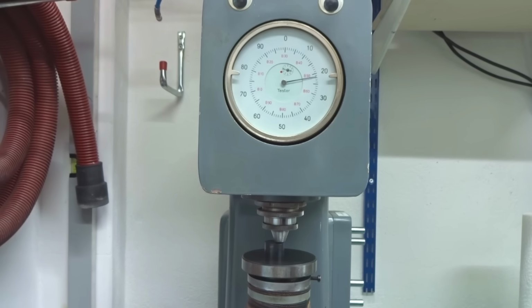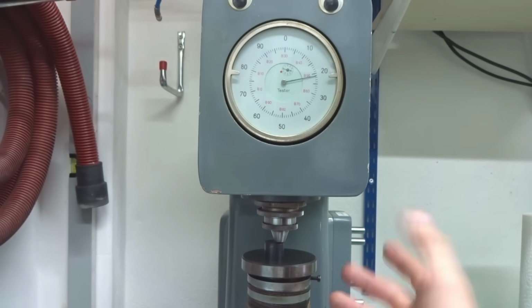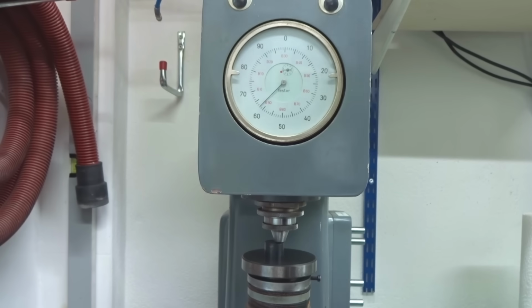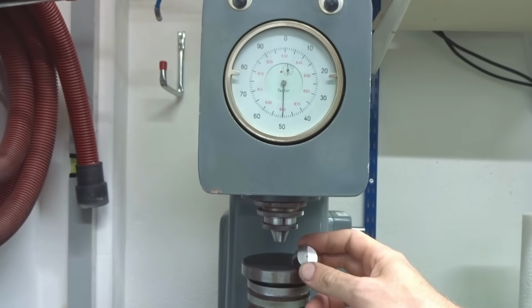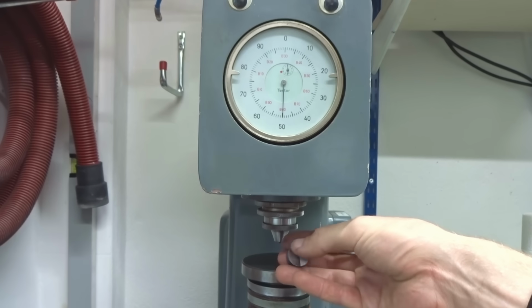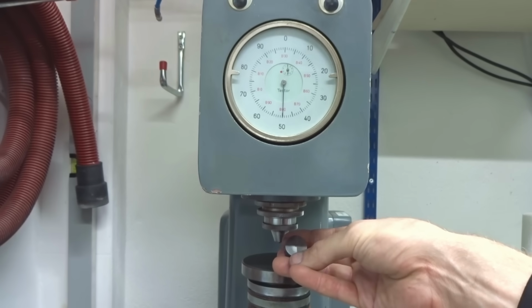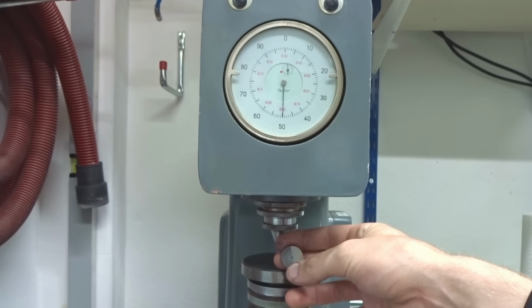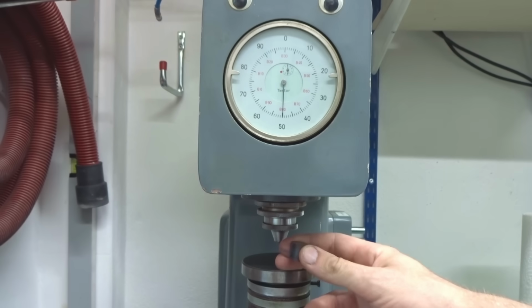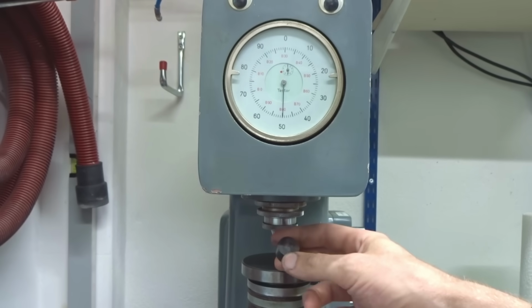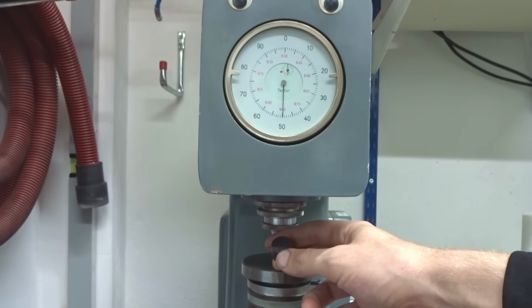I think you can see the difference between the sanded side over here and the surface ground side over here. So this is now on the sanded side where I just removed the scaling on the sanding plate. And this gives us 62 Rockwell C, which is very comparable to the result I got on the surface ground side. It goes to show even just rubbing off the scaling to bright metal improves the performance of the hardness tester by a lot. This is way closer to the real reading than what we got before on the scale.